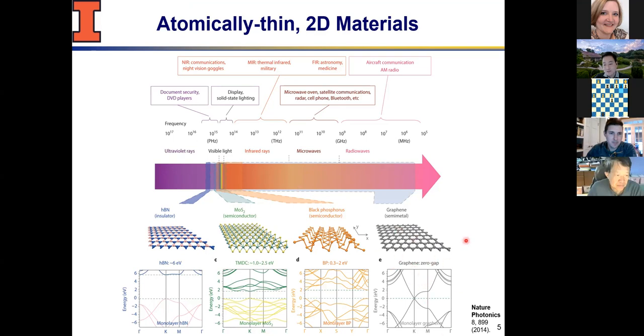It's just shown here. It's interesting just to think that these 2D lattices are stable in ambient. That was one of the very early controversies in the field because the 2D translational symmetry is not supposed to exist according to these famous theories, because there are thermal fluctuations. That was resolved by recognizing the fact that these materials are never very, very flat. Mathematically speaking, there are always out-of-plane corrugations, and that's really something that we started to notice, and I'll talk more about.